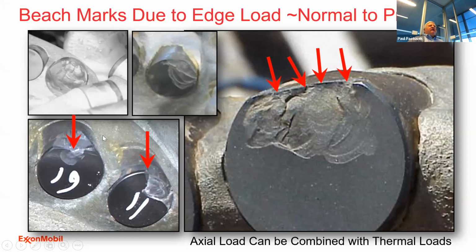So this was actually an axial hit. This one has multiple beach marks with multiple directions, suggesting a bunch of hits. Could be junk, could be some flakes and debris as well, but multiple fractures in that normal direction. And then you see this one, that's cutter number one, and it is angled a little bit toward the inside. This is also cutter number one, and it's coming in way from the inside.